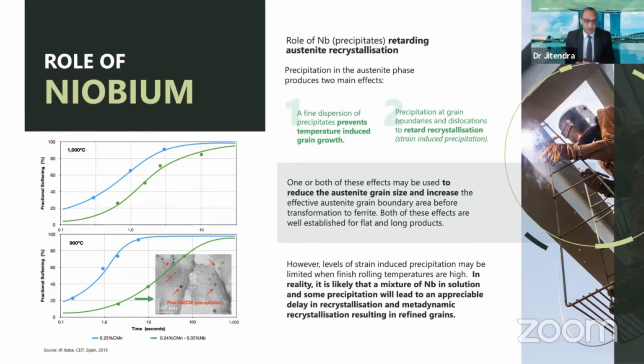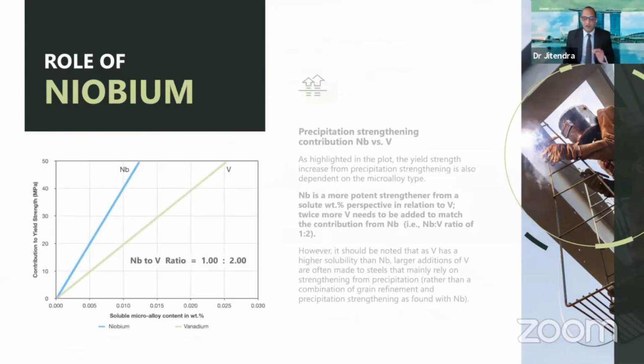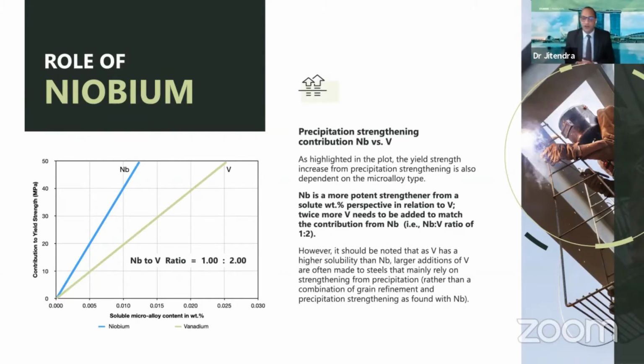But it shows that at very low levels of niobium here, you can see delays in fraction recrystallization. And this just shows that even at a higher temperature of 1,000 degrees, the top graph finishing, we'd still see a delay in recrystallization. And it's this mixture of delaying the recrystallization, but because we're finishing hotter, we're still having niobium available to precipitate, very similar to vanadium, to give us a very small fraction of precipitation strengthening as well. And these two points will give us that extra strengthening even at these ultra-low niobium additions. The graph here shows the benefit of niobium compared to vanadium, and typically we'll have niobium providing twice the amount of strengthening contribution compared to vanadium. So again, there's a benefit here from using very low levels of niobium, as you can see here.